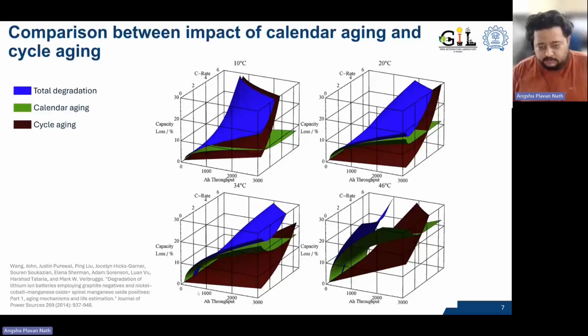If I look at the 34 degrees Celsius figure, your calendar aging pretty much always dominates over your cycle aging. What that means is, for a situation such as India, where temperatures are pretty high, calendar aging is going to dominate battery degradation compared to cycle aging. For V2G, the V2G cycles just affect your cycle aging and not calendar aging. So what it may show is that maybe V2G doesn't have as much of an impact. We'll see in the later slides what it actually does. But again, the highlight here is that calendar aging is a much more dominant factor compared to cycle aging.